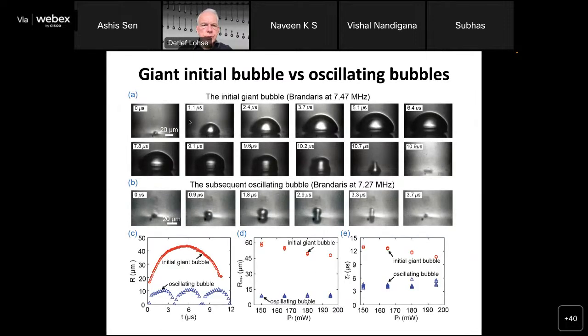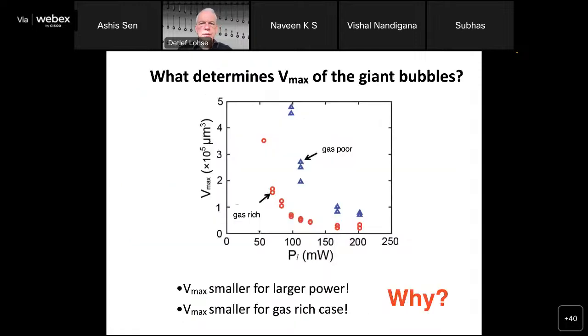So when we look into this giant bubble on a time scale of microseconds, we see that it gets huge, 40 micrometers radius here. And the later bubbles are all much smaller. If you compare this initial giant bubble, which is 60 microns typically, with the oscillating bubbles later, they are around 10 micrometers. It's still not the bubble which then grows because of diffusion and outgassing. So this is only at the very, very first moment. You see that after 10 microseconds, it's already gone. So without a high-speed camera, you don't see it.